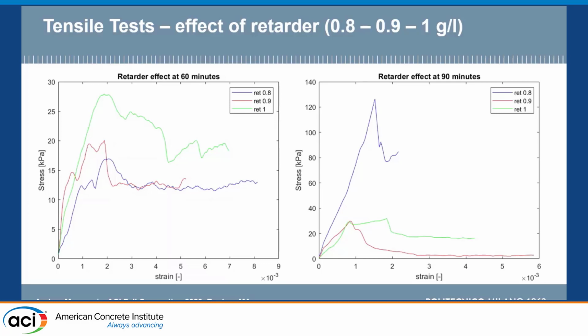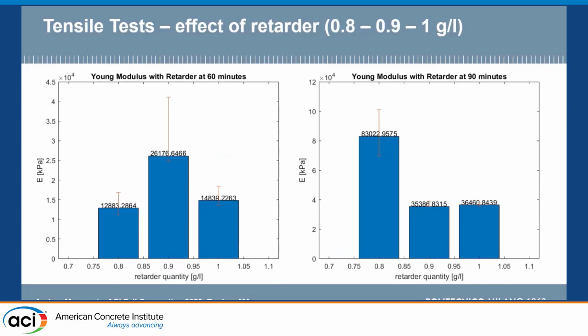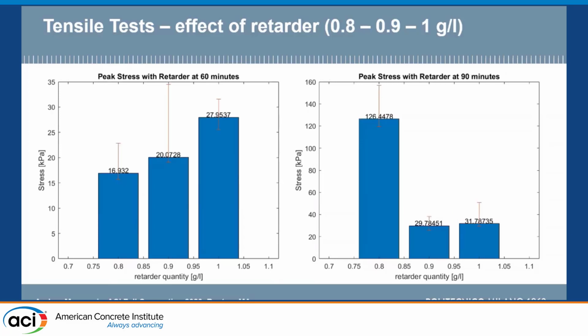In fact, for 0.8 gram per liter of retarder, there is an order of magnitude of difference compared to the other two quantities of the retarder. And this is more explicit by looking at the Young modulus. In fact, no clear trend at 60 minutes, whereas we can see instead a dependency on the retarder, as for the least quantity of the retarder we have the double of the stiffness compared to the other two quantities for 90 minutes.